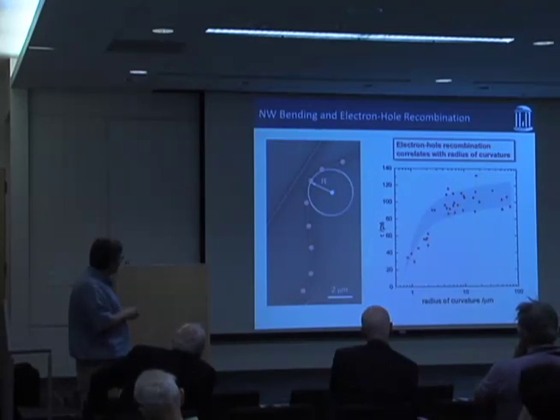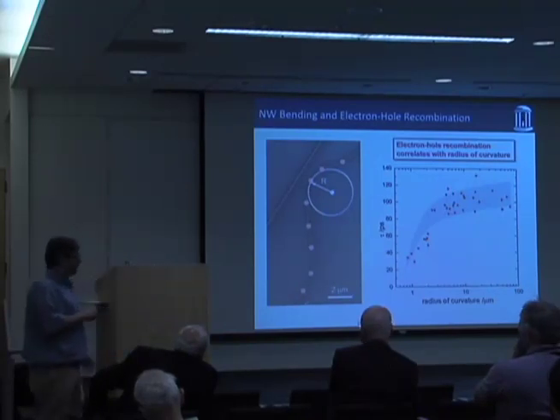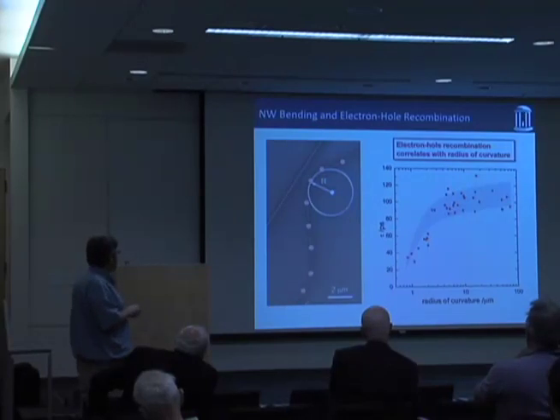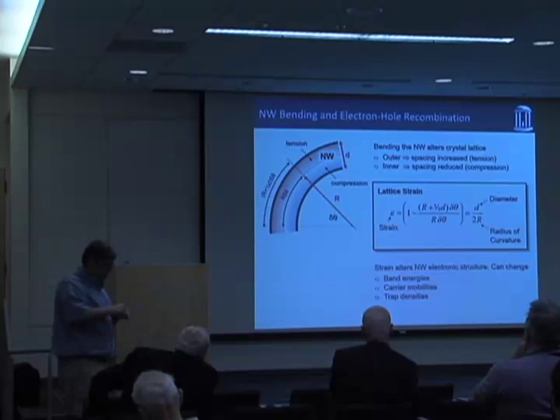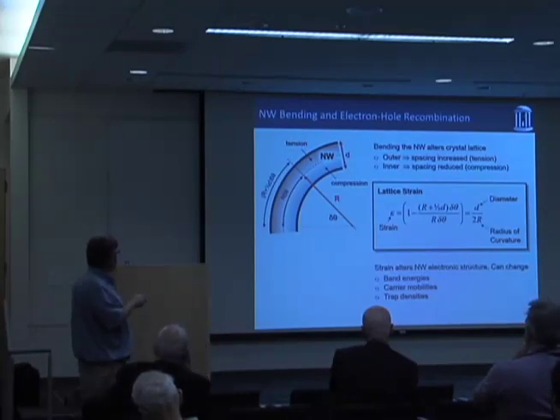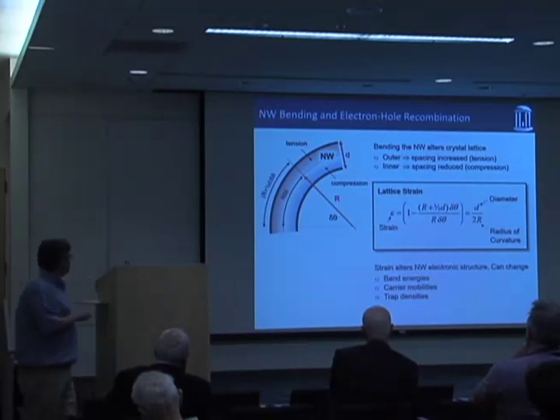This slide is like 6 months old, and I have many more points that I could put on there, and the correlation is better. And it turns out that when you take this wire and bend it, what you're actually doing is straining it. One side of the wire is in tension. On the other side, it's in compression. And you can quantify that strain with a really simple formula. If I know the radius of curvature and the diameter, I can get the strain.